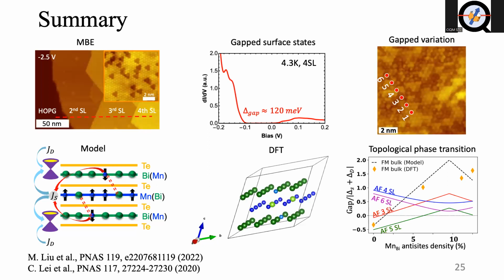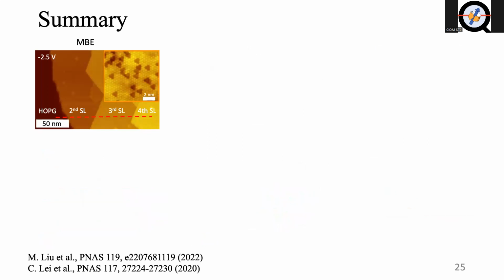Yeah, but there are pros and cons in those two methods. So it depends on which recipe the group starts with, and then how they optimize along that way. I'm just curious because it seems like in STM, when you do the bulk cleave, it always cleaves with the bismuth tellurium layer. So when you image it, it's always on the bismuth tellurium layer, but can anyone cleave there, because there's no natural cleavage between those central layers, and no one has actually measured the manganese tellurium.